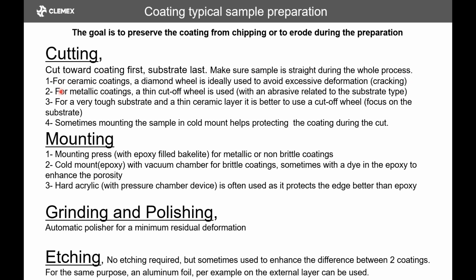And so there are various types of coatings, so there are various methods of cutting them. Most of the time for a ceramic coating, if it's thick enough, a diamond wheel will be used because the ceramic will be cut better with diamond. And if you have metallic types of coatings, you can use a regular cutoff wheel that is generally made for the substrate. Especially if you have a tough substrate and a thin layer, it's better to use a cutoff wheel all the way, because if you have an austenitic steel and you try to cut it with a diamond wheel, it's not going to work very well. So you need to work with a cutoff wheel that will work for very hard material.